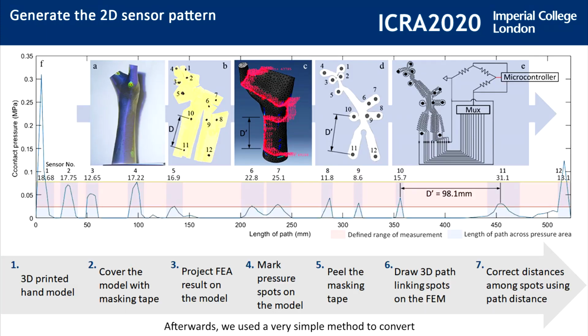Afterwards, we use a very simple method to convert the 3D pressure distribution of the FEA result into a 2D flat sensor pattern. The 3D distribution was projected on a full-size 3D printed hand model using a projector, and all pressure spots were marked manually on the surface of the model, which was covered with masking tape. If we flatten the masking tape, we could get a rough 2D sensor pattern.